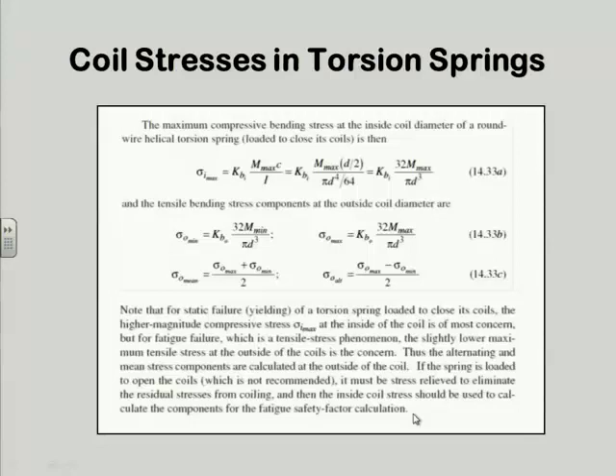This is often done after making a welded part, because the welding process puts all kinds of crazy residual stresses in, because you're locally heating with your electric torch some strip where you're bringing in molten material to make the weld, and then you let it cool, and it shrinks and gets distorted, and you leave a whole bunch of stresses hanging around in there. So if that's going to be subjected to any serious loading in service, you probably want to cook it in the oven and get it back to more or less as-made steel conditions. Okay? That's what they're talking about here. But in the same breath they're saying it's not recommended that you load them that way.